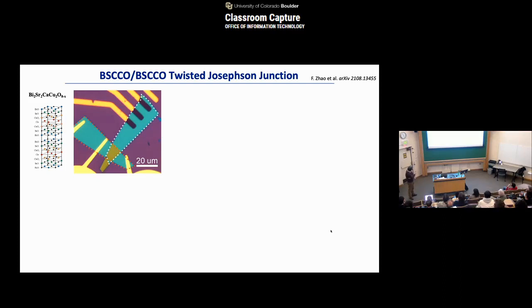We can start with one of the high temperature superconductors, bismuth strontium calcium copper oxide. The name itself is very long, but it is a really nice layered system. In fact, it has nicely cleavable van der Waals layers in the crystal. So one can, in principle, cleave this crystal and study the single layer, but also you can just put them together. The simplest heterostructure you can make is basically to cleave them and put them together with a twisting angle to make a twisted structure, right?